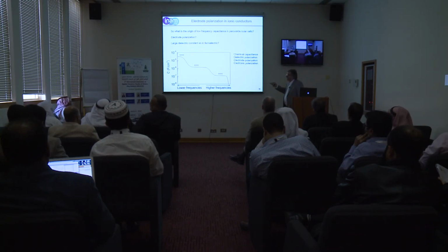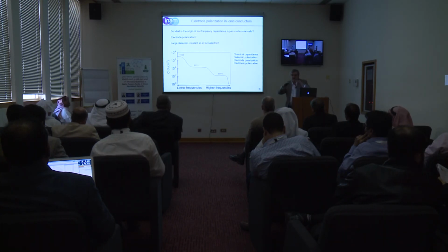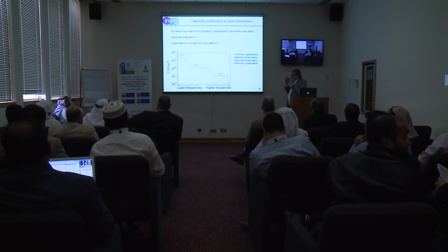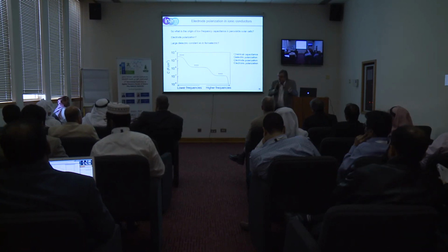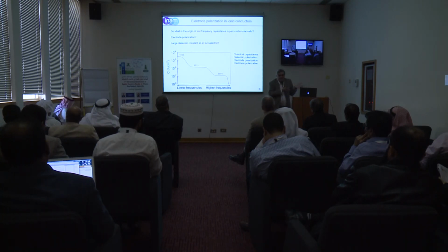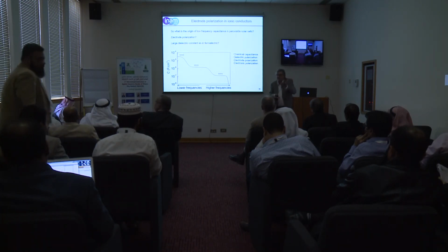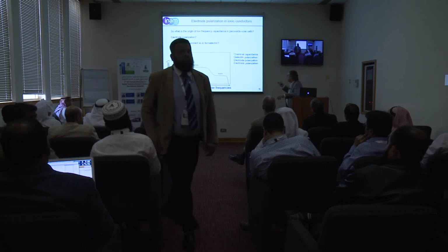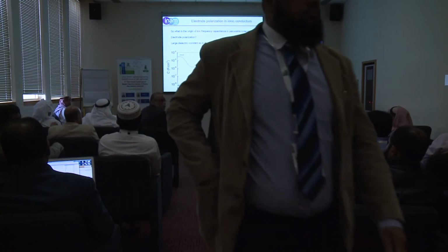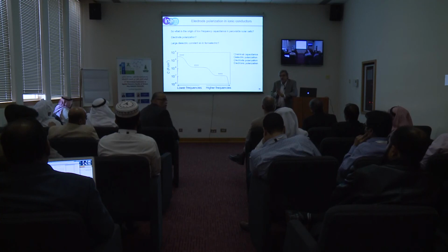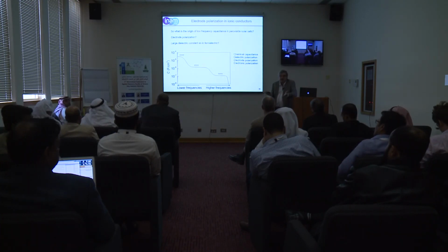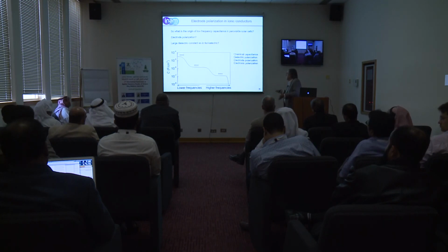First thing, in a semiconductor, chemical capacitance, related to increasing the density of states in the material. It must be somewhere, but maybe it's small, we cannot see it because it's overlapped by a bigger capacitance, but it must be there because we know there is separation of Fermi levels, etc. Second, the electric polarization. Well, perovskite has a big dielectric constant, so you can have very big dielectric polarization.